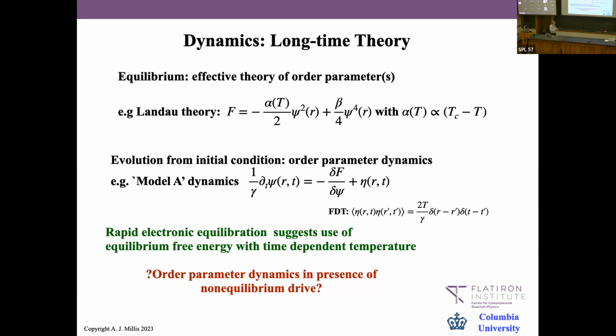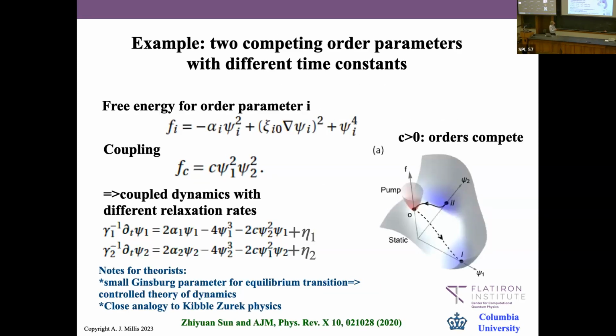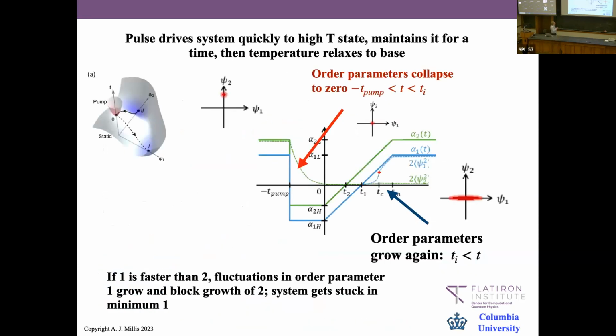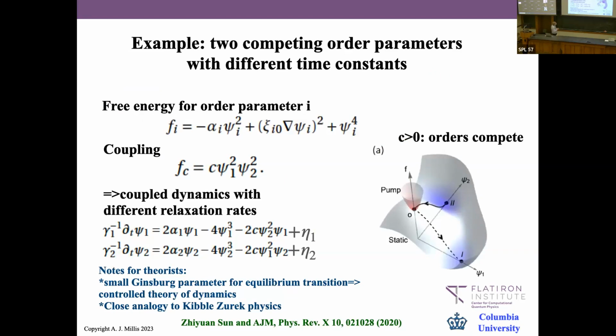Okay, so this gives you an equation that can be solved. Here, what we did was we took two order parameters. As it were, going back to my superconducting example, a charge density wave one and a superconducting one. Each one has its own Landau theory. There's some cross-coupling. If we make a positive coefficient, they compete.